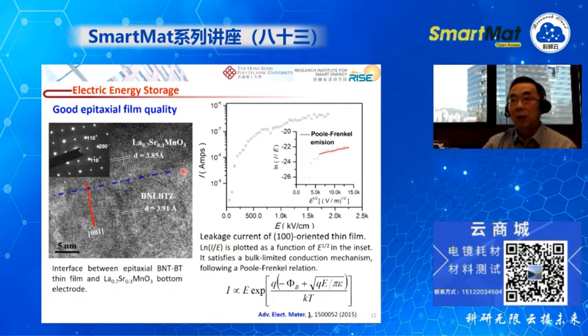Then we also examine the cross-section of the film on the substrate. We use this lanthanum strontium manganite as the bottom electrode, and we deposit our ferroelectric film, and we can find there is a very nice epitaxial relation between the film and the substrate. When we do the electron beam diffraction, we found no splitting of the spot.